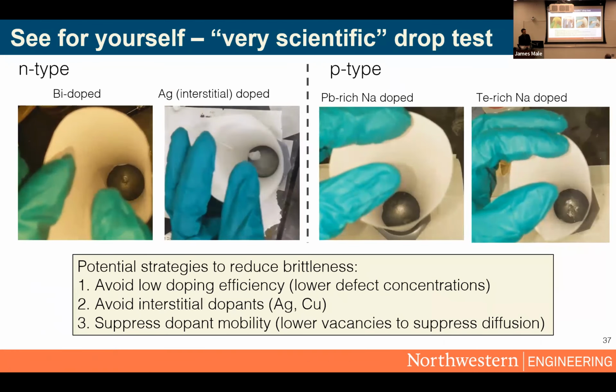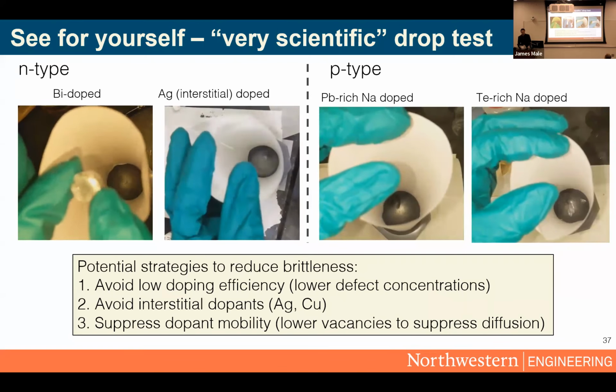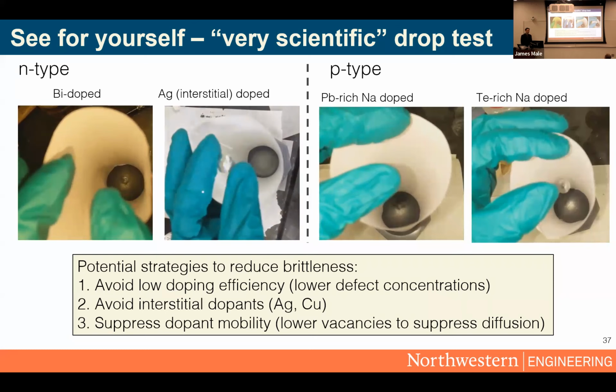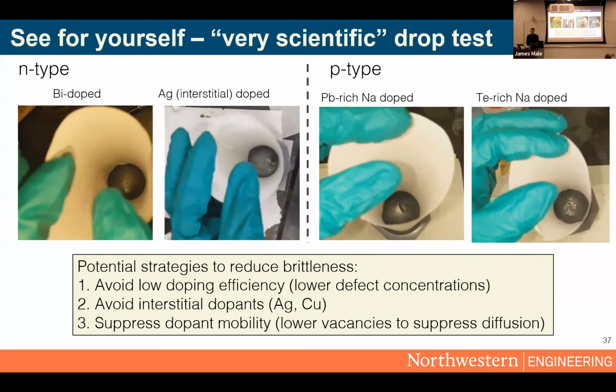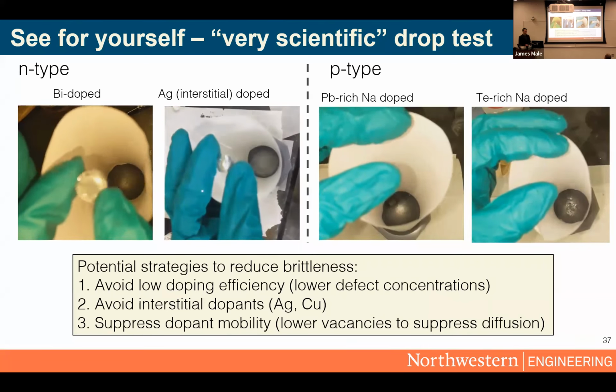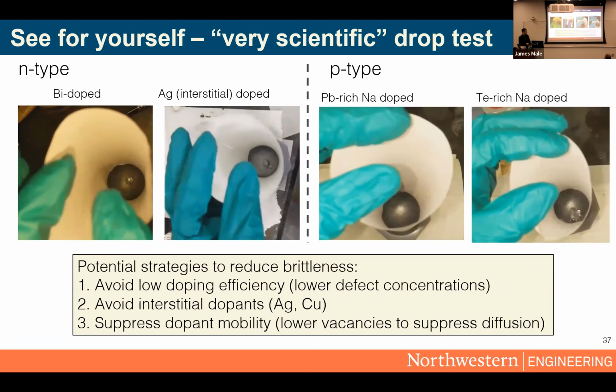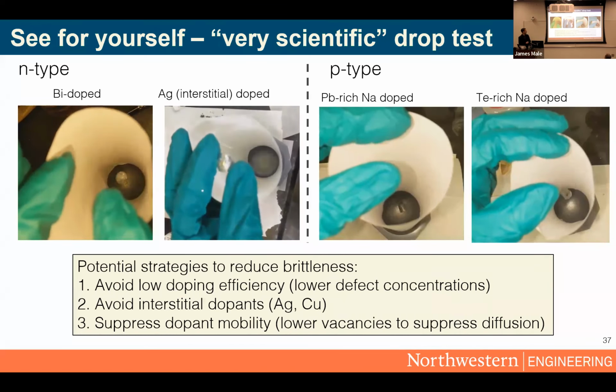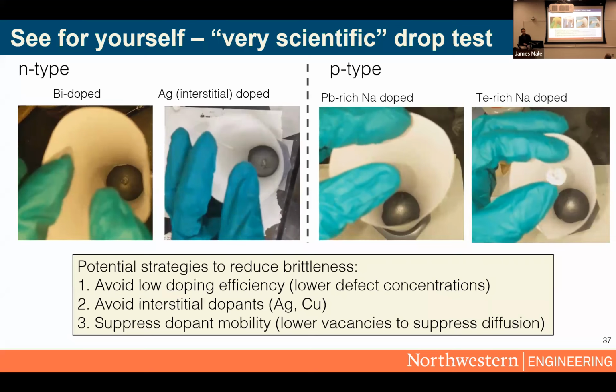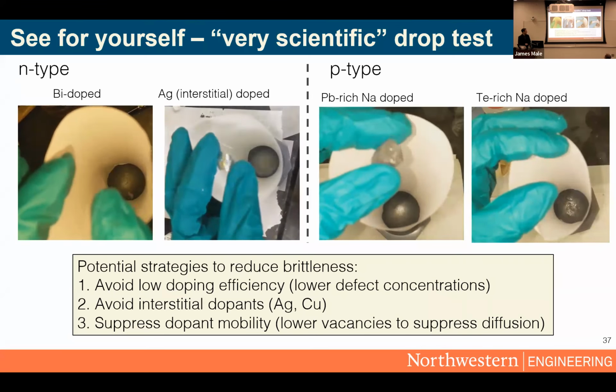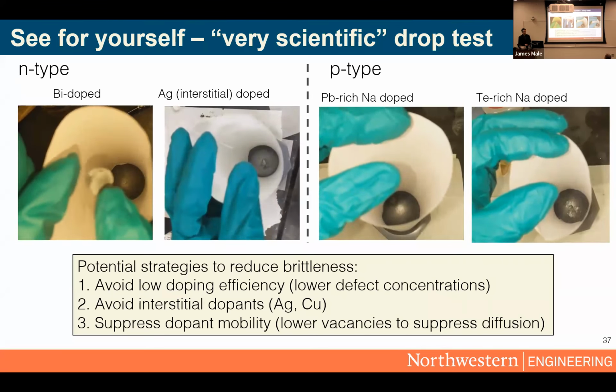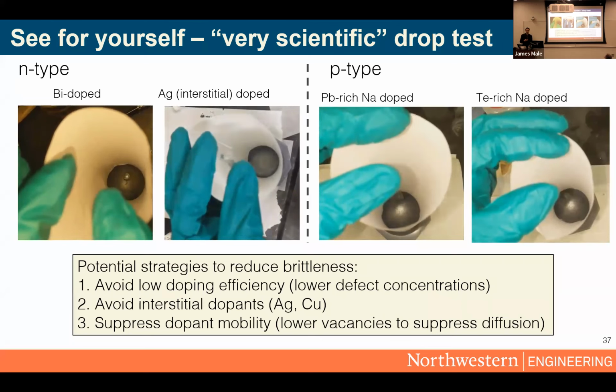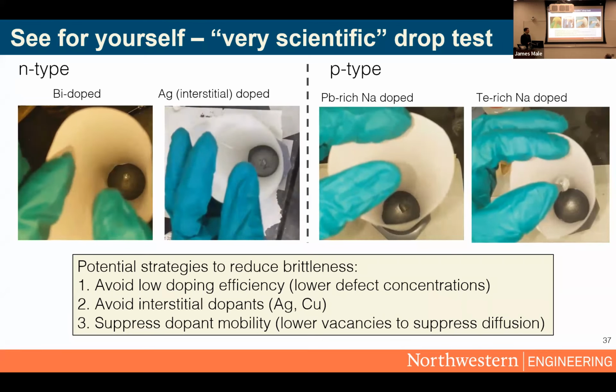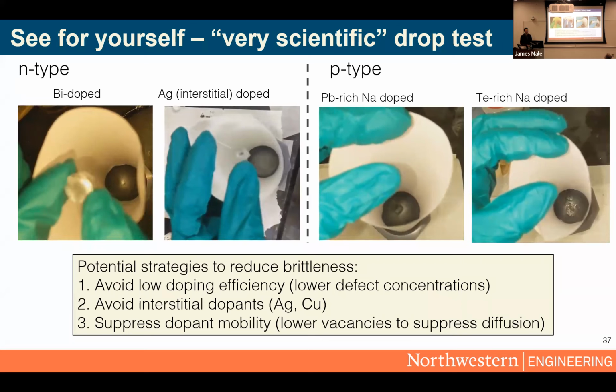All right, so to conclude my mechanical property section here, I'm going to use these videos as I talk through the key points. So the first point here is that lead telluride with a high doping efficiency dopant tends to be more robust. So for example, bismuth doping in N-type lead telluride gives you a very tough little ingot. If you use instead an interstitial dopant, you start to reach brittle materials. So silver, copper dopants gave me very brittle performance.